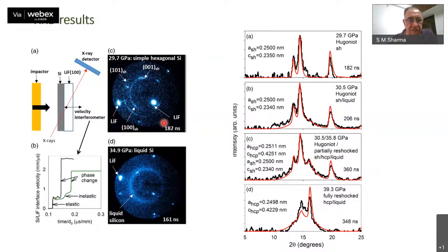So at a higher stress, at something like close to 35 GPa, all these other peaks vanish and you have a broad hump. This again is because of certain single crystal features of lithium fluoride or leftover unshocked silicon. So one can show here explicitly, through the loss of several X-ray diffraction peaks, that the material has actually molten. In fact, it cannot necessarily be stated that it is molten. It could be that it is amorphous, but through careful interpretation in terms of the known melting curve, etc., one can conclude that it is indeed molten.